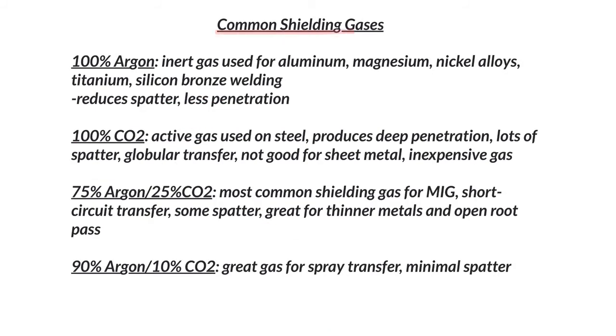So the common shielding gases include 100% argon, an inert gas that we use for aluminum, magnesium, nickel alloys, titanium, and silicon bronze welding. Okay, we don't use 100% argon for steel alone. You know, there's always a mix. All right. Argon itself reduces spatter. It also doesn't allow us to have as much penetration. Actually, what it does is you get a penetration that kind of looks like a finger when we're welding on a piece of metal. So it gets thin in the middle here.